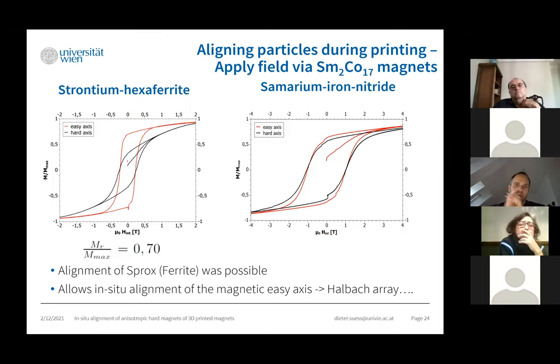So if you look at the easy axis and hard axis loop, the easy axis loop is the direction of the measurement, which is parallel to the applied field during the printing process, and it is quite similar to the hard axis loop. So you hardly see a remanence enhancement, whereas for the strontium hexaferrite, you clearly see that the remanence in the easy axis direction is significantly enhanced.